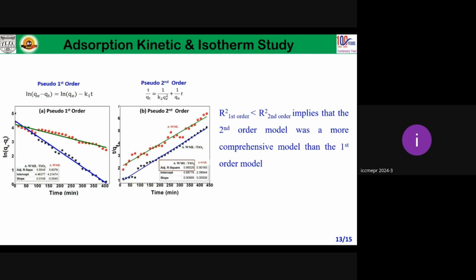Kinetics and isotherm studies were also carried out. Pseudo first order and pseudo second order models were applied, and it was observed that our synthesized material gave a better result in pseudo second order, because the R square value for pseudo second order is higher than for pseudo first order. So this is a more comprehensive model than the first order model.